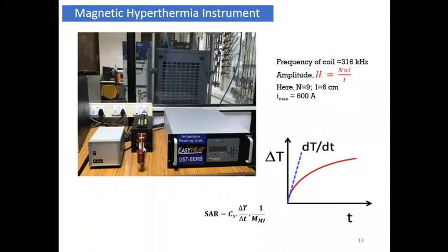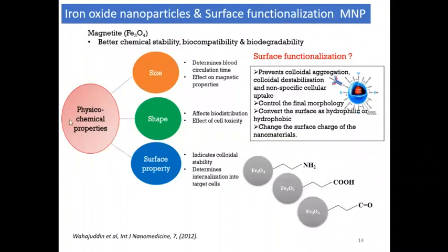So there will be a temperature sensor probe, and we can get the heat. And with respect to time, at what applied field and what frequency, how much heat is generated, we can measure. And from the slope, delta T by delta t, this is temperature versus time, we can measure the SAR values. Fine.